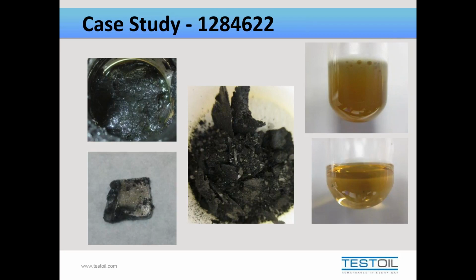We ended up being able to determine through the analysis, though, that the system had been severely contaminated with silicone grease, and that it was also determined that the lubricant itself had experienced oxidation. However, this really wasn't the primary concern. The primary concern was the silicone grease that had most likely caused the bearing to fail, and the system would need to be thoroughly cleaned with a solvent in order to remove the contaminating silicone.